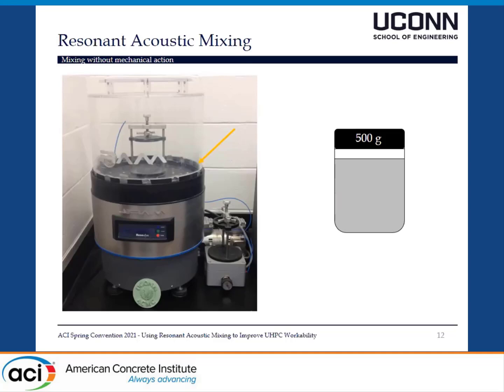And this acoustic pressure wave creates two mixing flow zones. The first flow zone is an intense micro mixing zone, approximately 50 microns in diameter. And the second mixing zone is a bulk mixing flow zone that encompasses the total container.